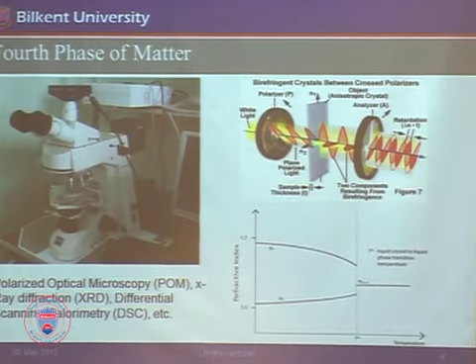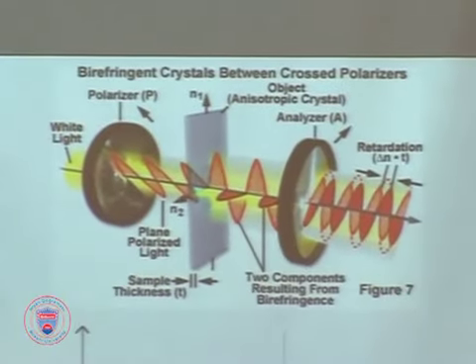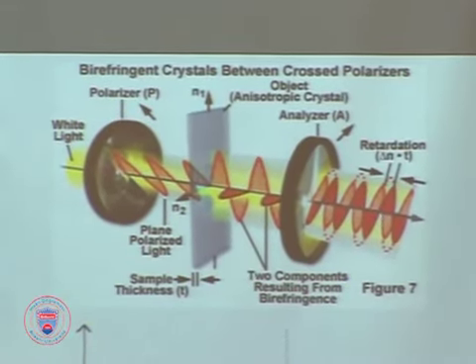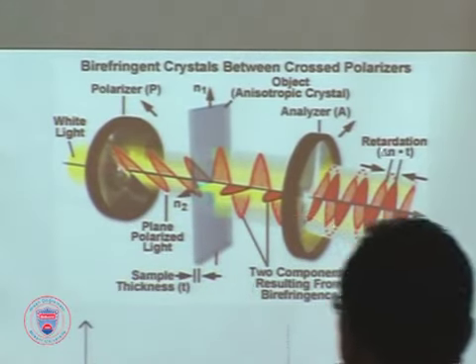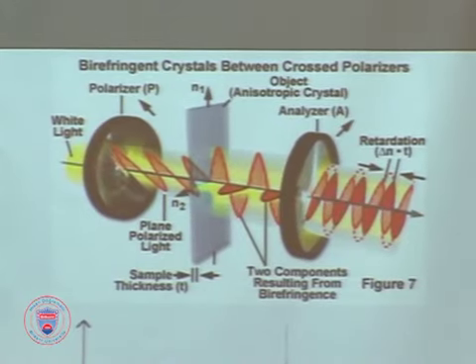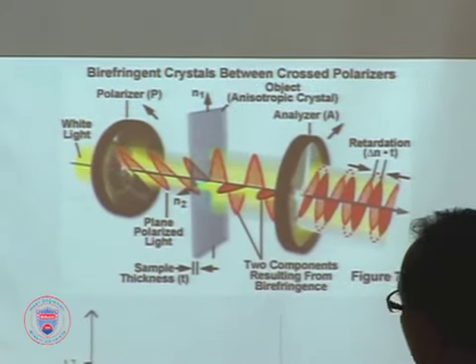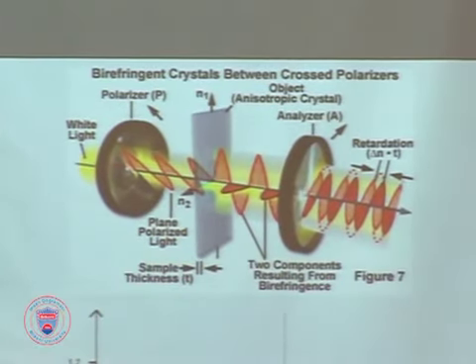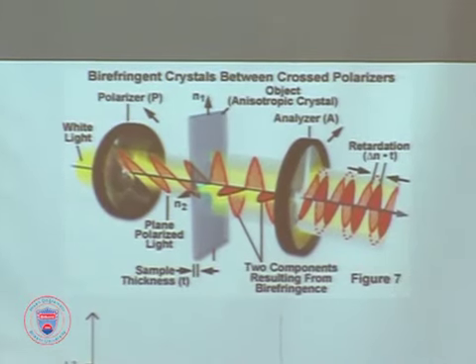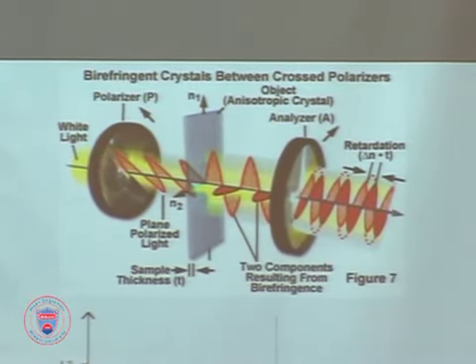And if you have the liquid crystal sample in between, and if this liquid crystal has two different refractive indices because of this orientation and everything, then it can change the polarization of this light. In a way, this analyzer is perpendicular. If this sample is doing nothing, basically, it comes out with this polarization, and on this analyzer, it gets stuck. You see nothing, basically. You see dark. Nothing goes through. The only time you see something after the analyzer is if your sample has to do something. And this something comes from refractive index, basically. These materials, if they have more than one refractive index, they can do this trick. Otherwise, they will just go through and nothing will come out.